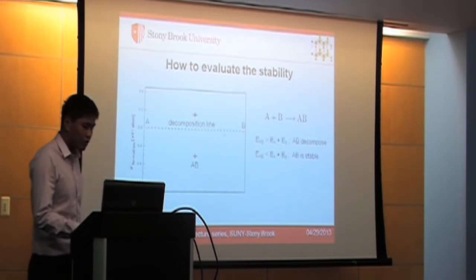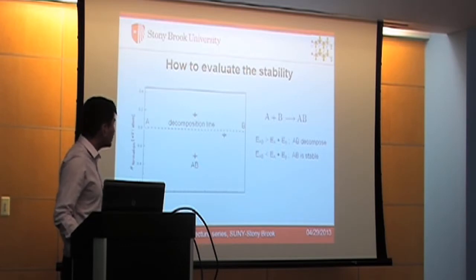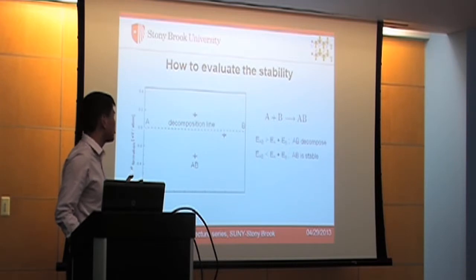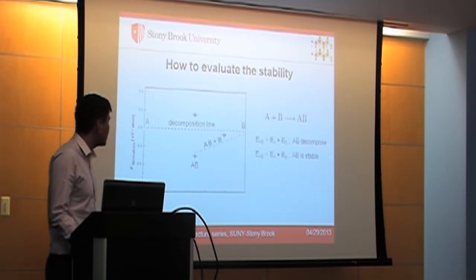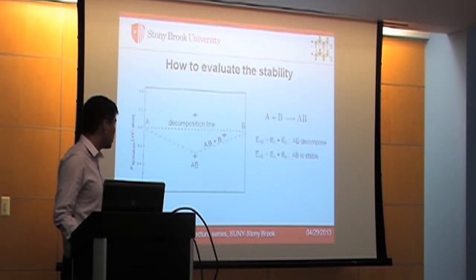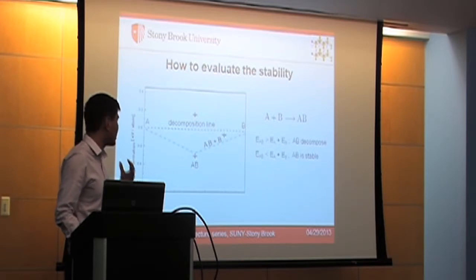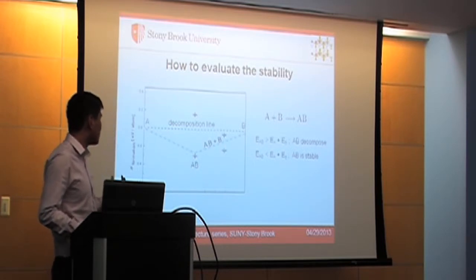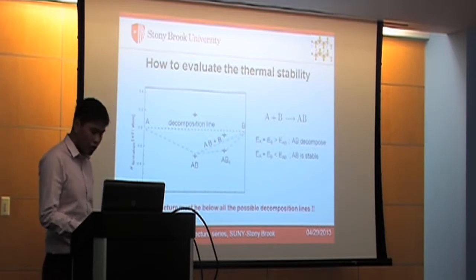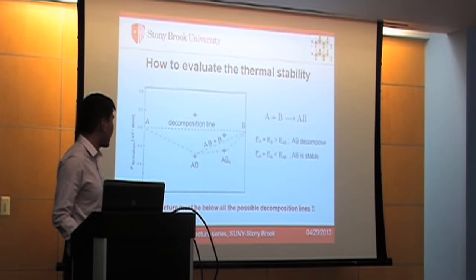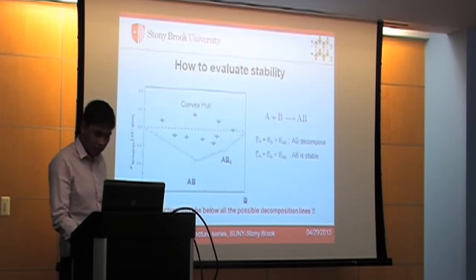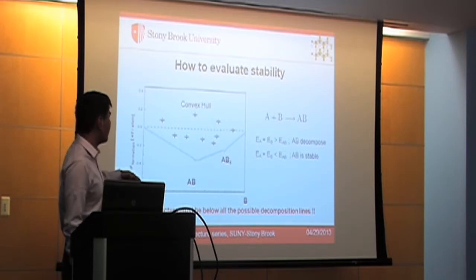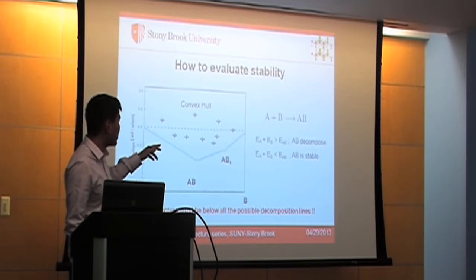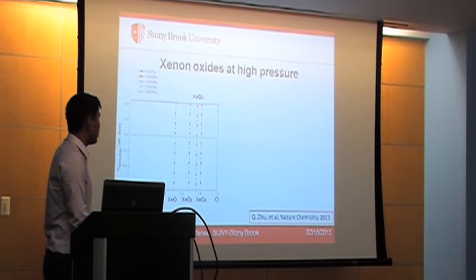If we have another composition, say AB4, from this picture it seems that this structure should be stable because it's below the decomposition line, as I mentioned. However, it will decompose into AB plus B, so it's still unstable. So the criterion for the stability of desired structures is that the energy must be below all the possible decomposition lines. So that's how we analyze these figures, these data. The stable structures will together form a convex hull geometry. So with this concept in mind, we can go ahead to analyze our results.